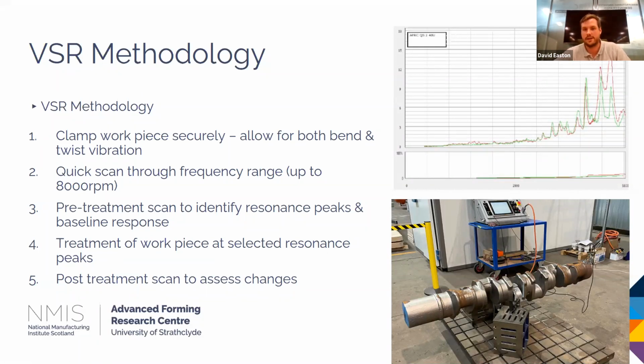This is a natural frequency of the system. To do the treatment itself, all we do is set the motor to that frequency and basically spend an amount of time at that frequency, typically 15 or 20 minutes. And then we do a post-treatment scan to assess.